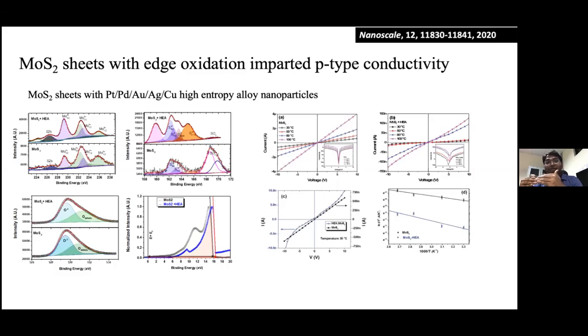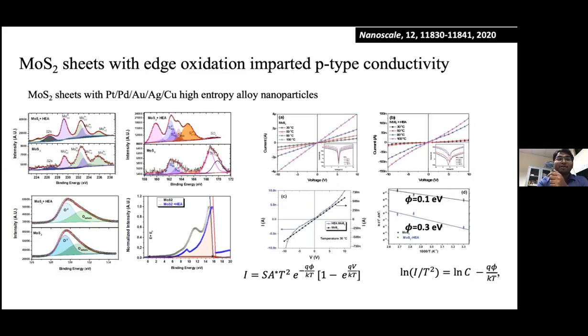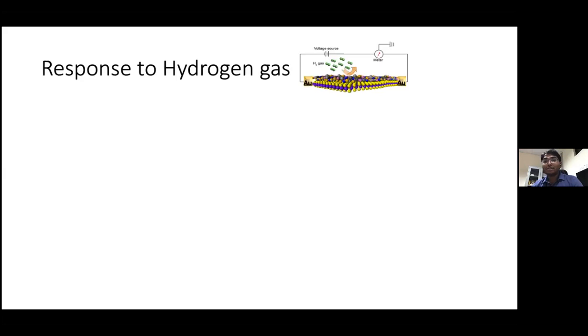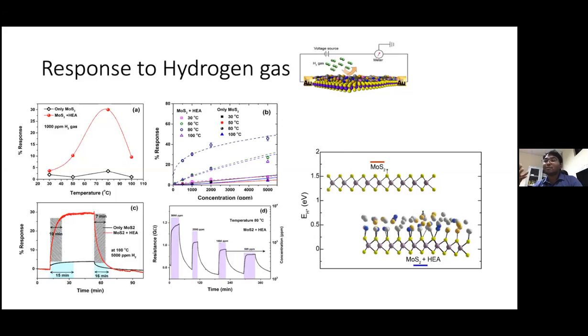So we analyzed these IV graphs with the thermionic emission model, which is routinely used for evaluating the barrier height. And what we found is that when the particles are put on MoS2, it actually shows a Schottky behavior with a barrier height of about 300 milli electron volt, and that barrier height is significantly high for room temperature as compared to the bare MoS2, which is around 100 milli electron volt or so. So how is that reflected in the response to hydrogen? This Schottky barrier is very sensitive to hydrogen.